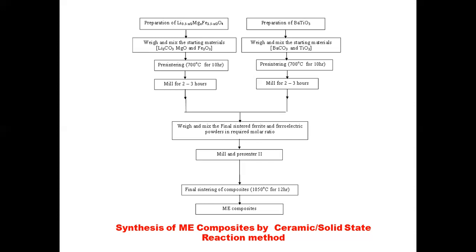But if you are taking pure water as a mixing agent, you will have to grind these compounds for a very long time to get a dried fine powder. So that is a problem. So generally, acetone is used to mix these compounds.